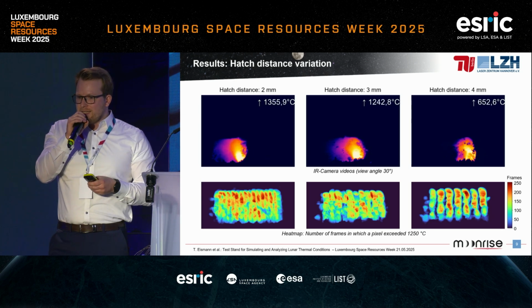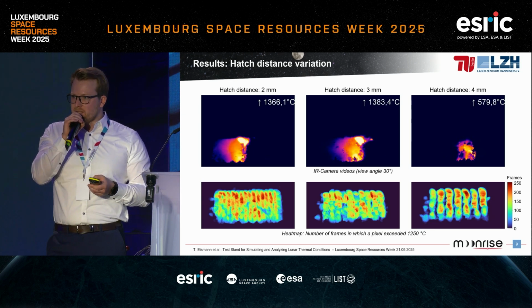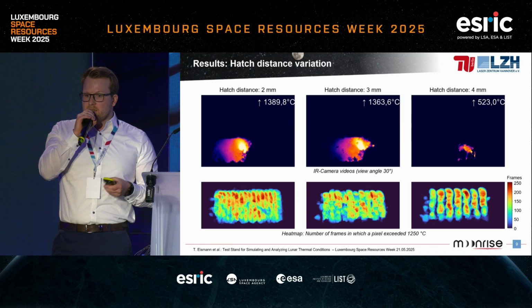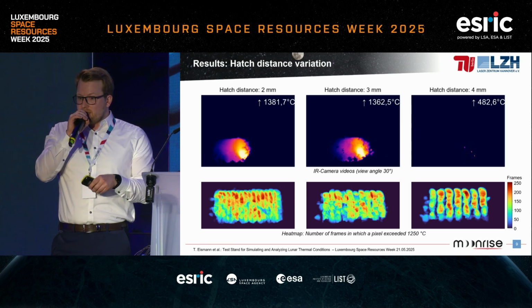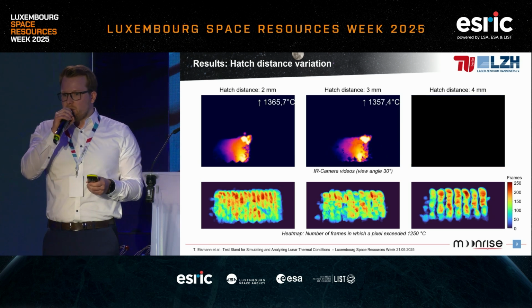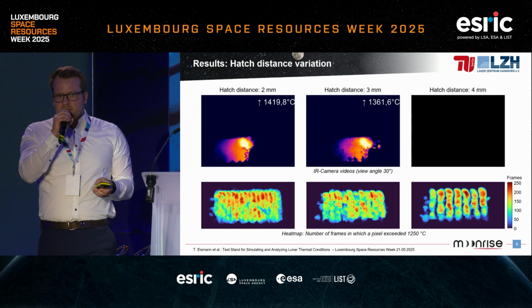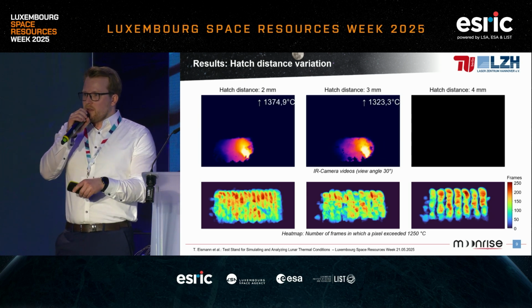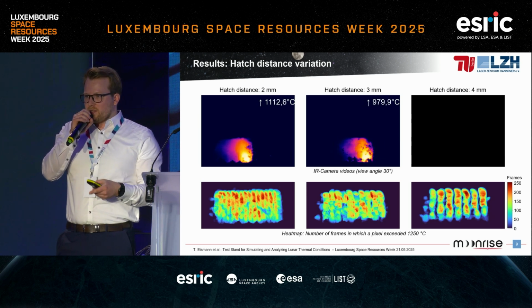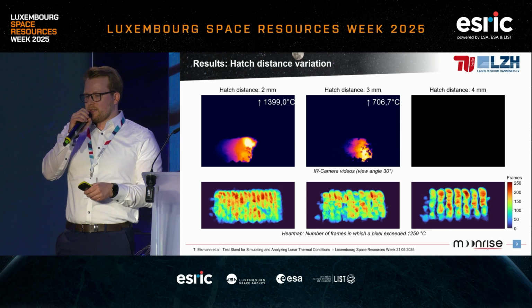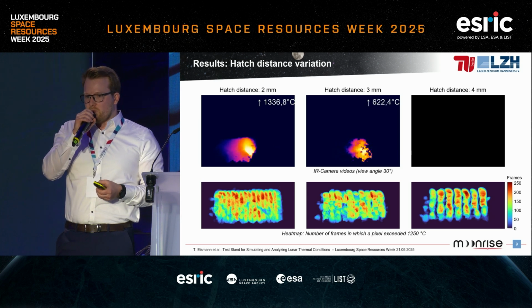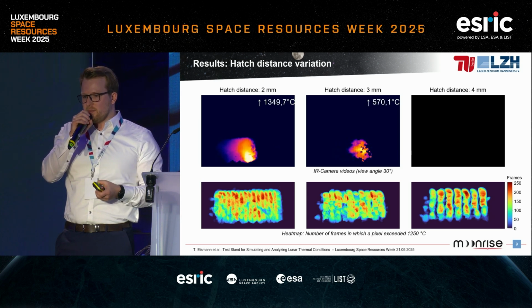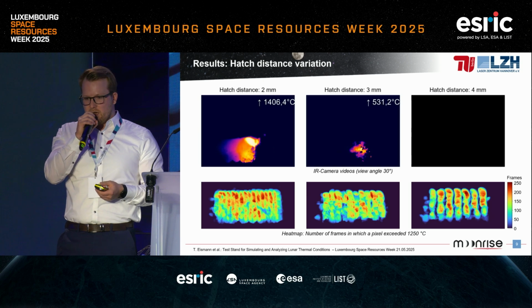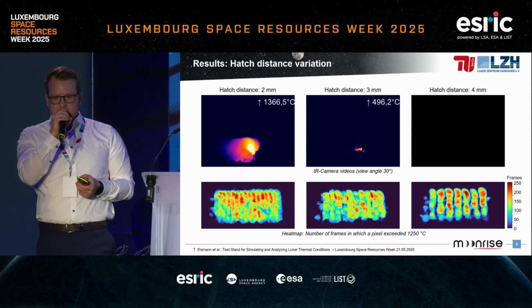And if we looked inside our samples, we would see that there's a higher porosity in the samples and that there are also some unmolten particles inside. But with that solution, with the infrared camera, we can see that right after the process, so we don't have to look inside the samples anymore, and that's why our process development will be much faster with that option now. And yeah, then we did another test with the setup.